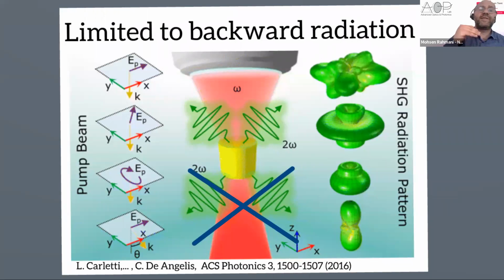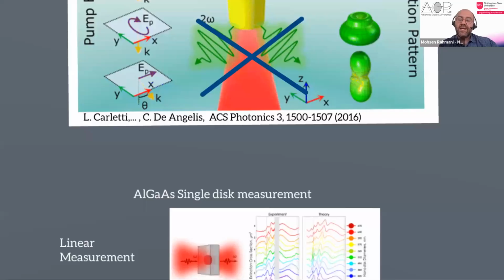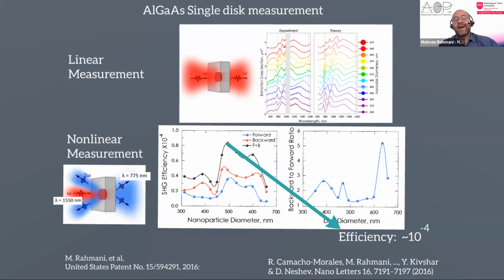But all of these studies which I mentioned are still on an opaque substrate, either gallium arsenide or thick gallium phosphide, that is not transparent in the visible range. That's why you cannot have it in both forward and backward. So although all of this research is very exciting and interesting, they were limited only to the reflection. So it was where we proposed a way to fabricate these gallium arsenide nanostructures on glass substrate, so that you could get signal from both sides, forward and backward, here in this paper.